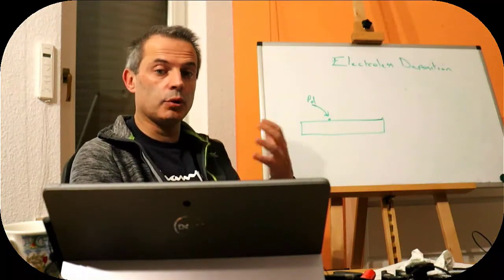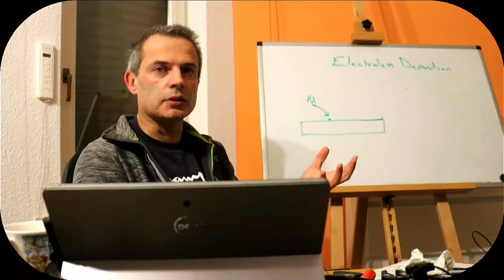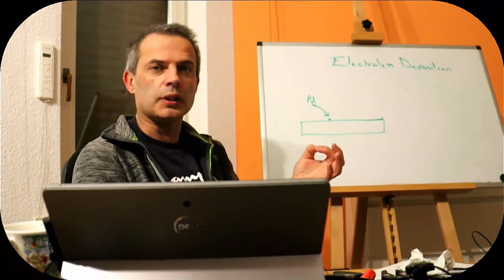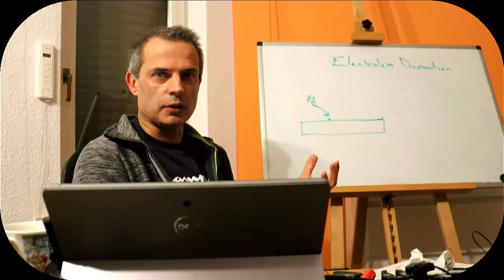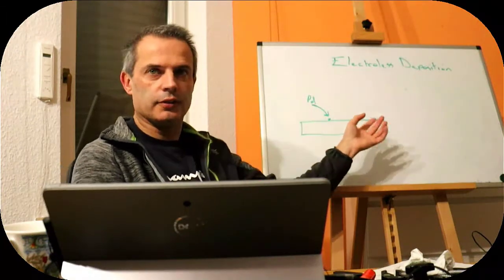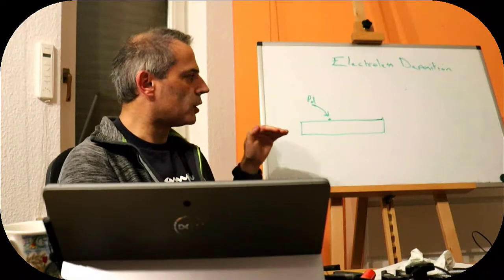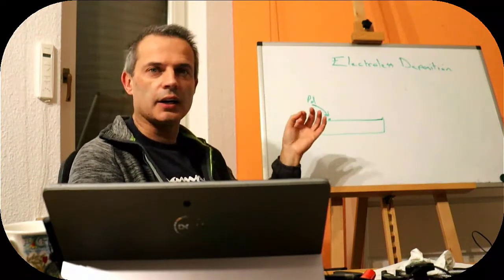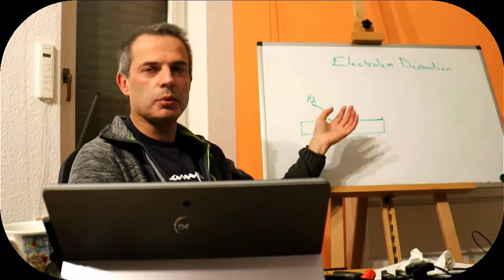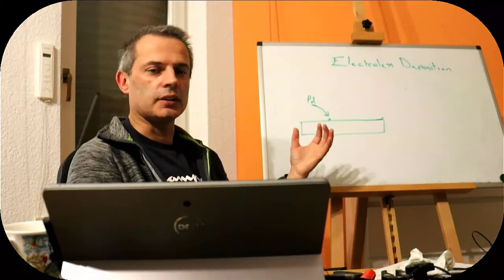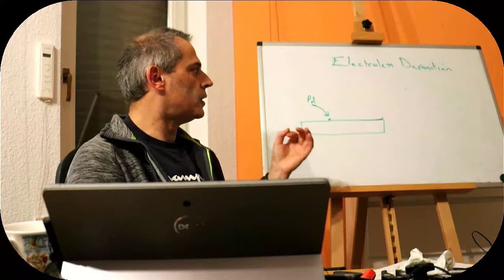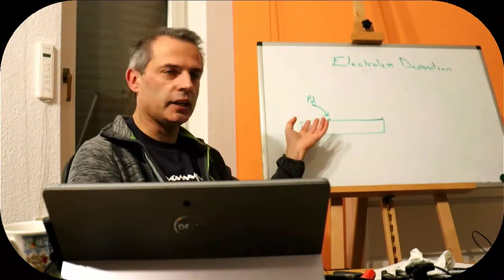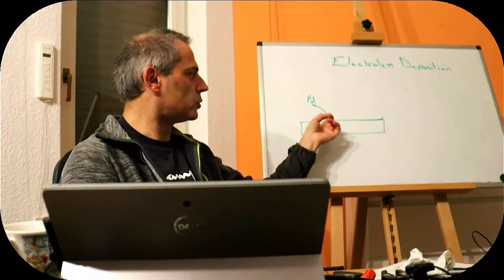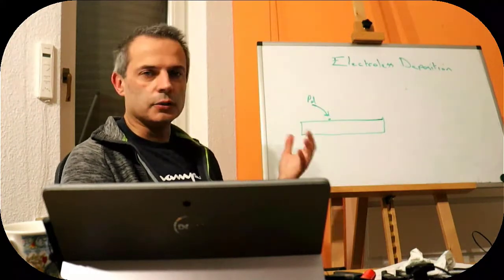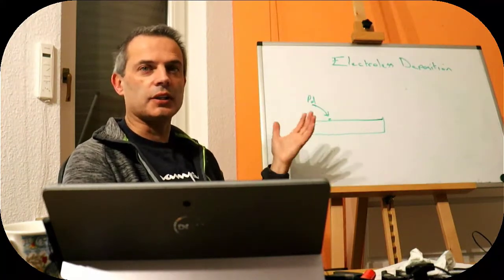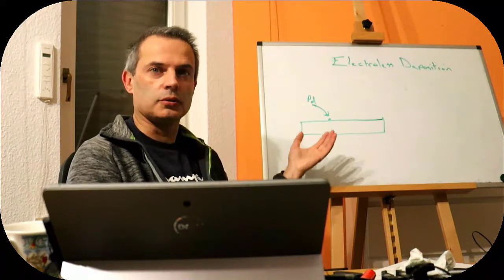So now we have the next problem, which is how do we get the palladium onto our surface, or whatever initial metallization that we need to cause it to grow. It doesn't have to be a complete film, as we just noticed. It can grow across the surface, but we do need a reasonable coverage of particles of palladium or some kind of catalyst on the surface to get it to go. They don't necessarily have to be super well attached, because the film will grow underneath them as well, but they do have to be there, and they have to be attached enough that they don't fall off in the bath and cause new problems to occur.